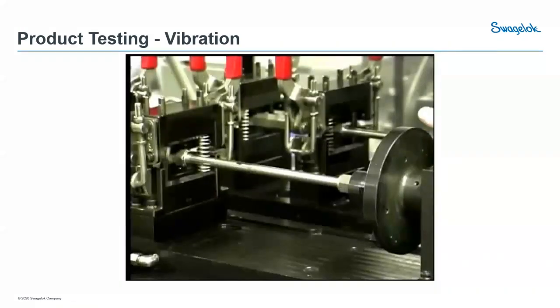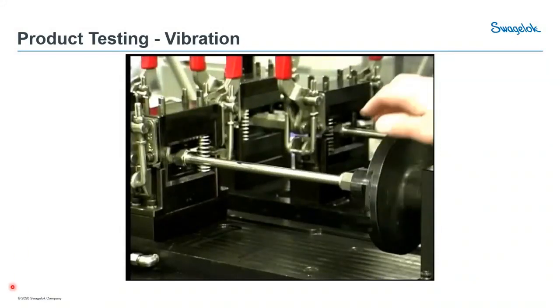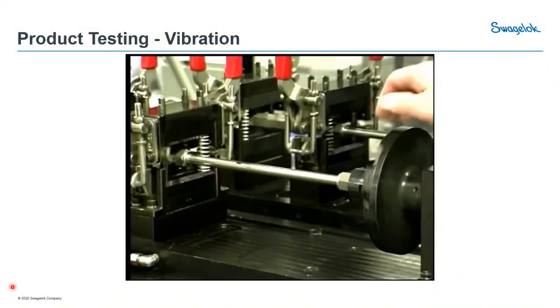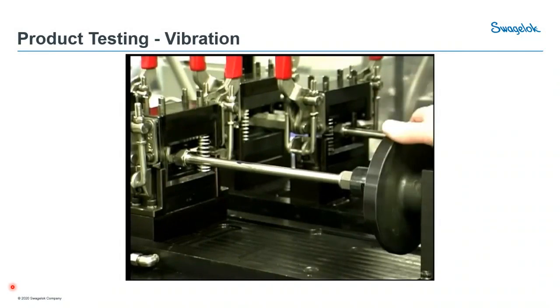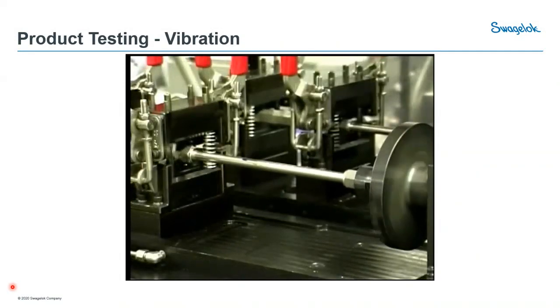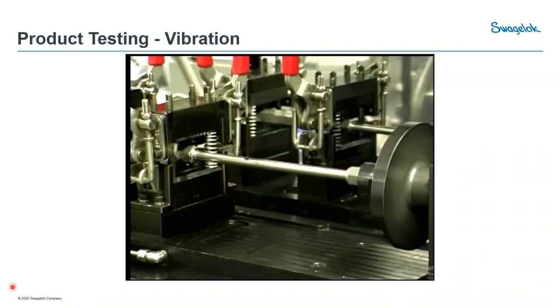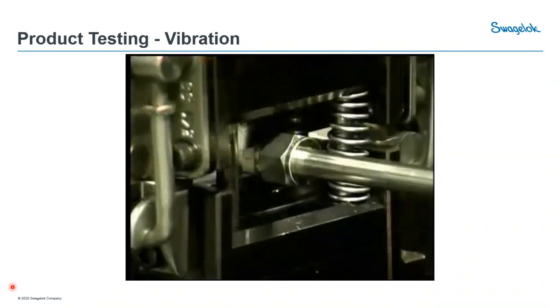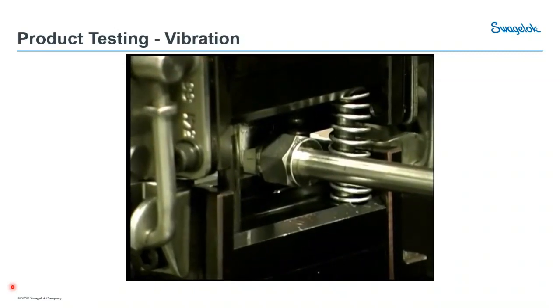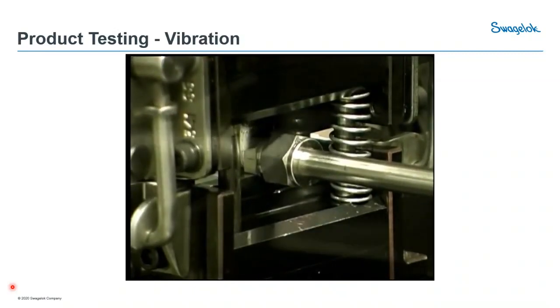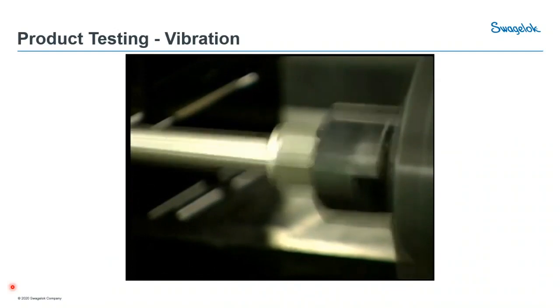Now looking here, here's an example of what that test looks like. So the left side of the tube is fixed. The right side is attached to that rotating chuck. Now this is pressurized to 3,000 psi, and it's a rapid test to simulate vibration that you might find in the field. This goes over a few days and ends up in millions of cycles of vibration. You can see the tube is vibrating back and forth, and this is how we perform that analysis to see how the tube fitting performs in vibration.